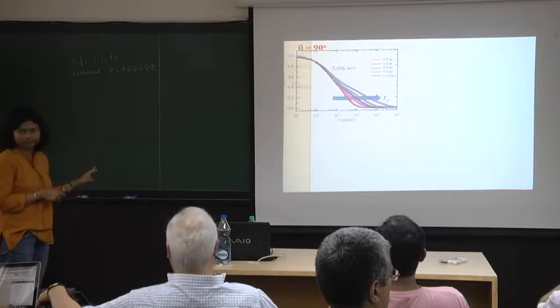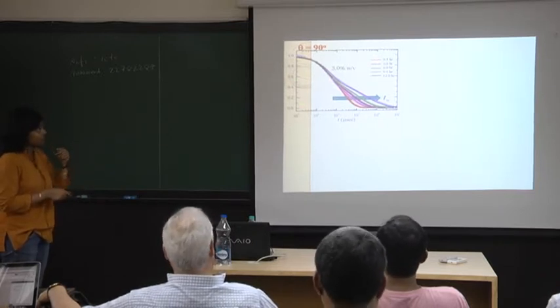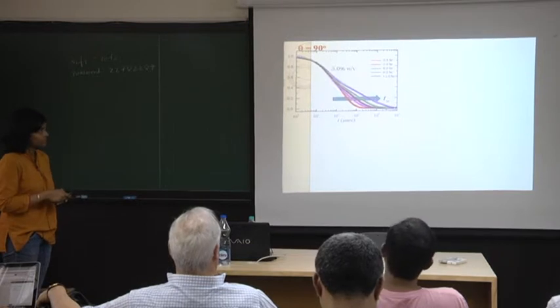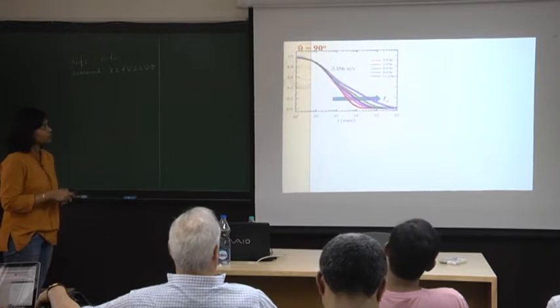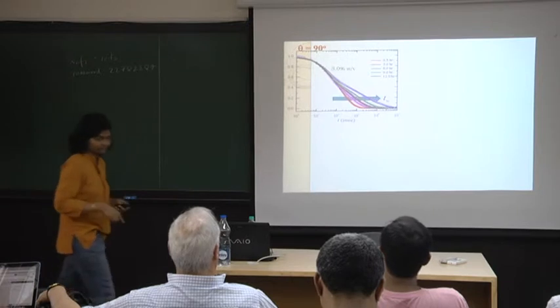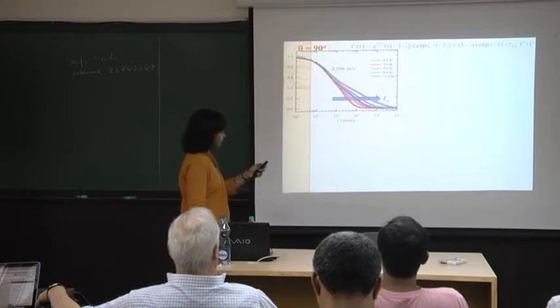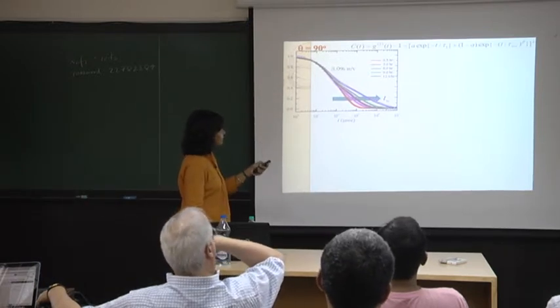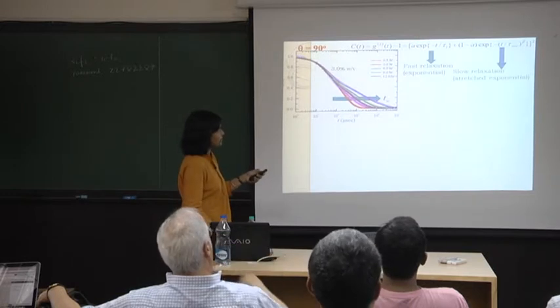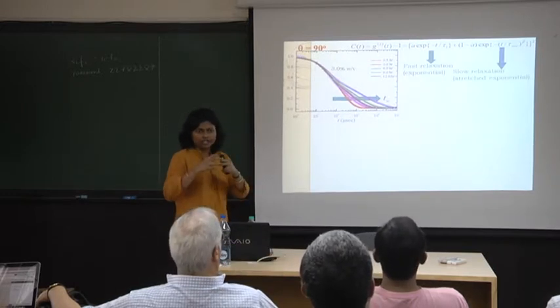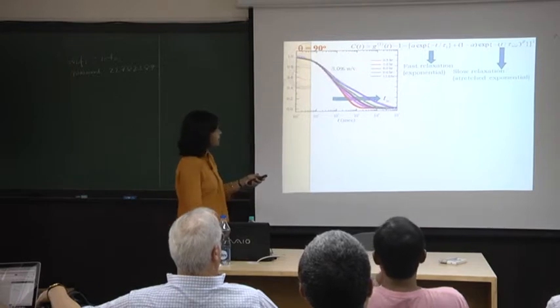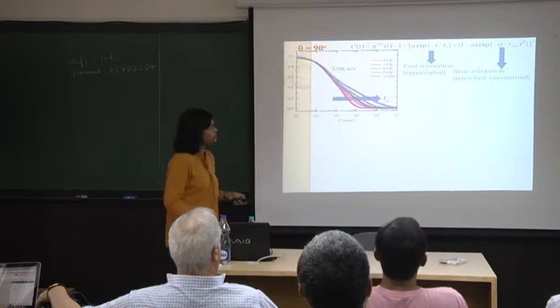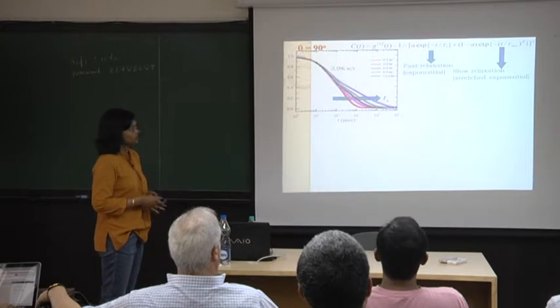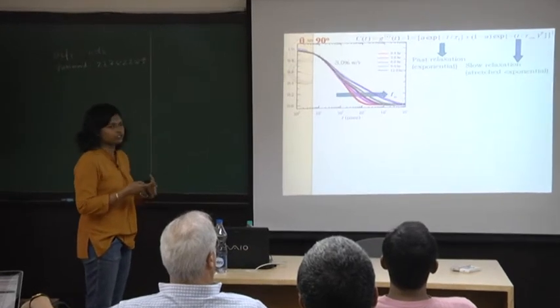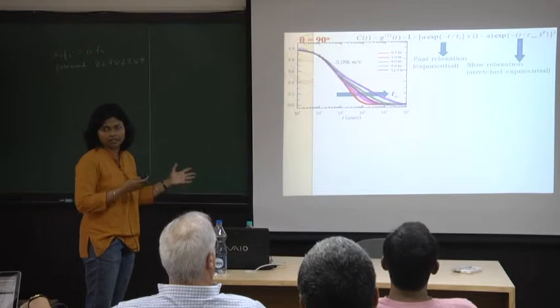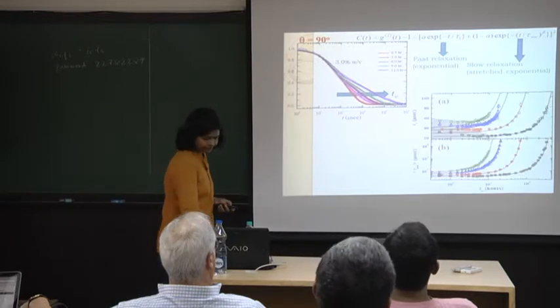You can see two things here. One is that you have a two-step relaxation process. The other thing is that as the age of the system increases, the slow relaxation becomes slower and slower. So we fit it to something like this. This is the fast relaxation bit. It tells you about the dynamics of the particles that are trapped in the cage. The second part, the stretched exponential part, is the alpha relaxation part, which tells you about how the particles are moving out of their cages.